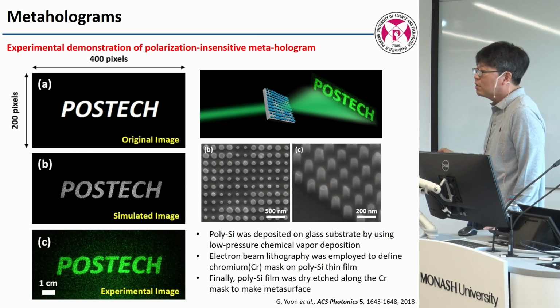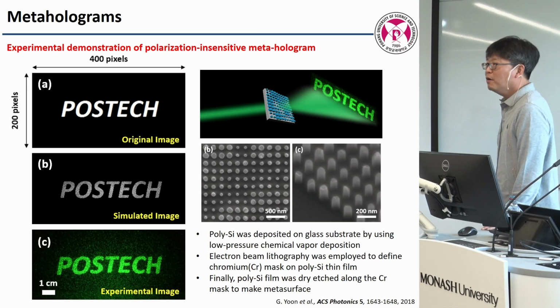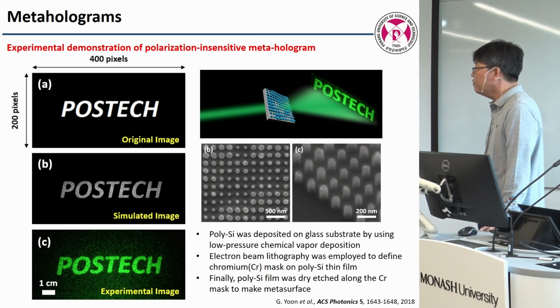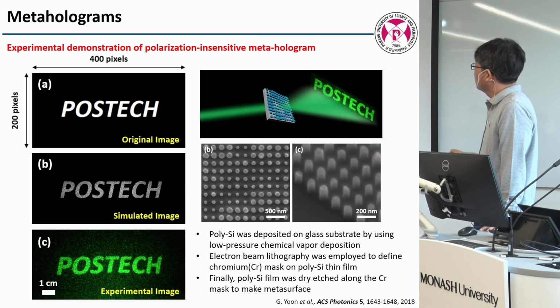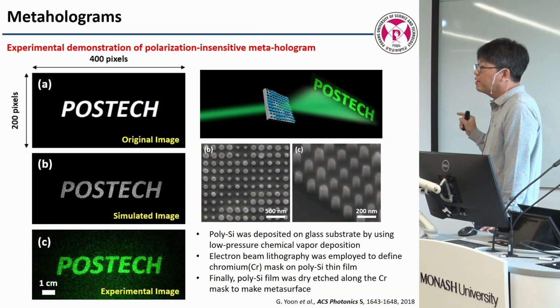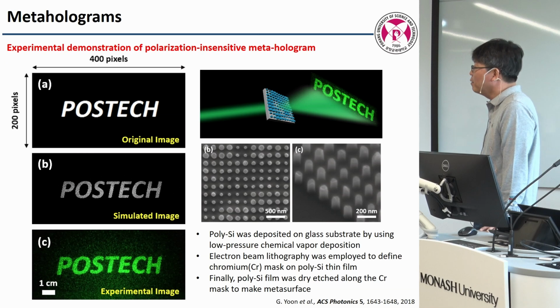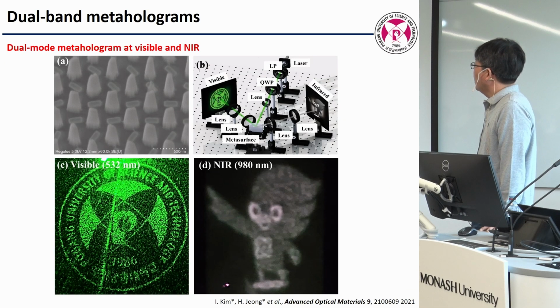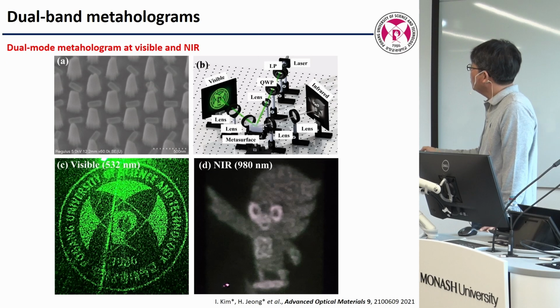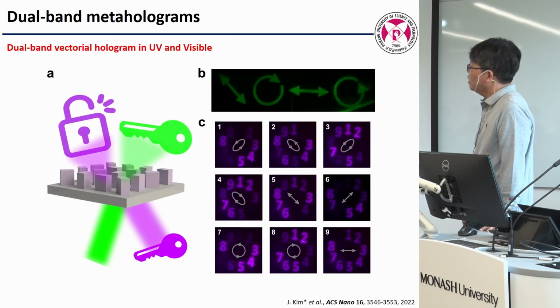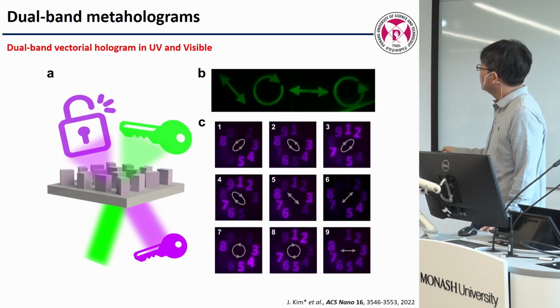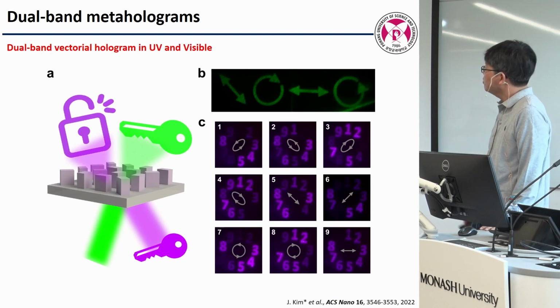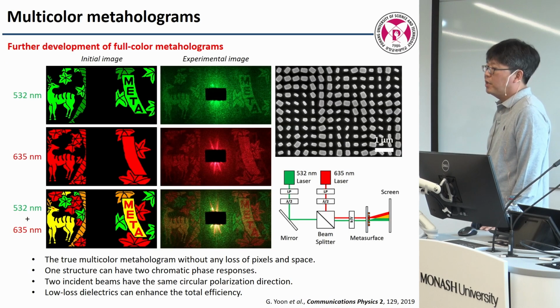So what we did immediately: green color, using polysilicon, easier fab, and transmission type. So efficiency increased to 7%. So okay, better, 7 times better, but still not enough. And then we used a dual wavelength, green by silicon, IR by this golden nanorod array, working independently in combination. And why not UV? Silicon nitride and silicon, so dual wavelengths again, UV and visible. And this is a two-color, aberration-corrected one.